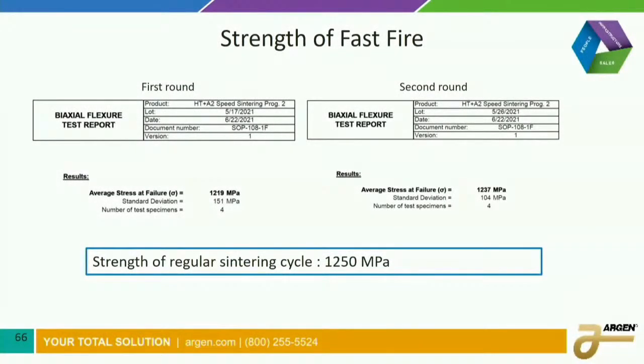On the strength, we did the strength two times because I didn't believe the first result. Our normal strength is like 1250 megapascals, and we got 1219 and 1237. So the first round of testing was very close. The second round of testing was a little closer. And again, these are just processing at 105 minutes, as opposed to the 450 minutes.